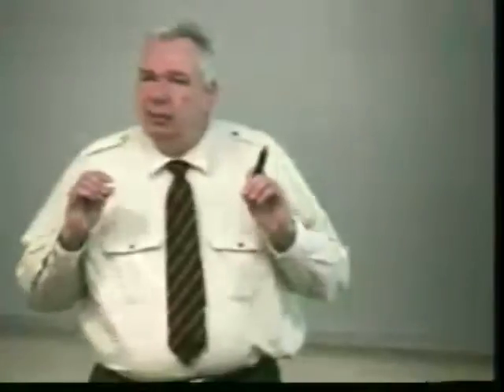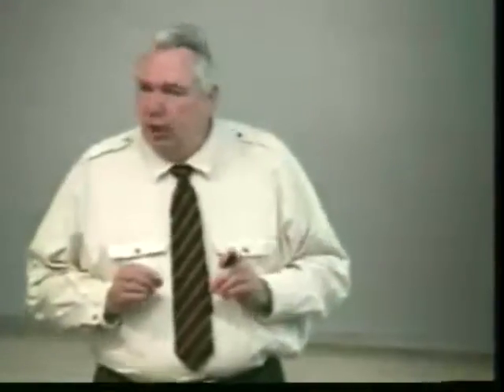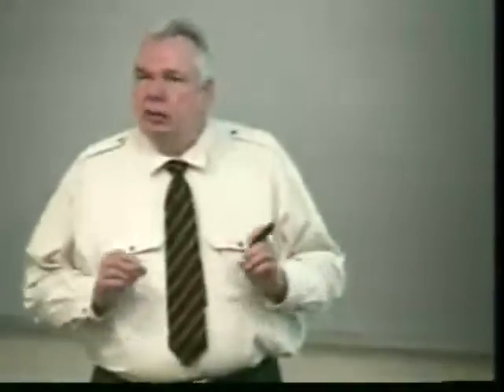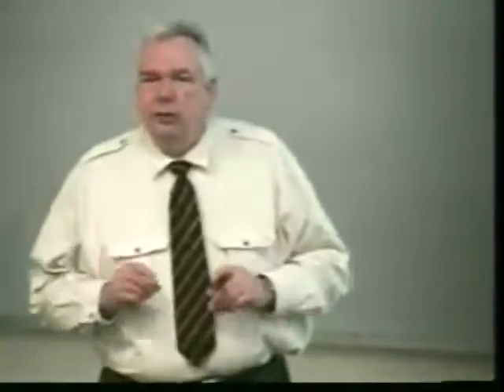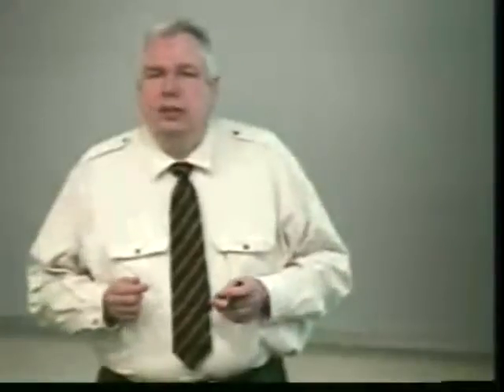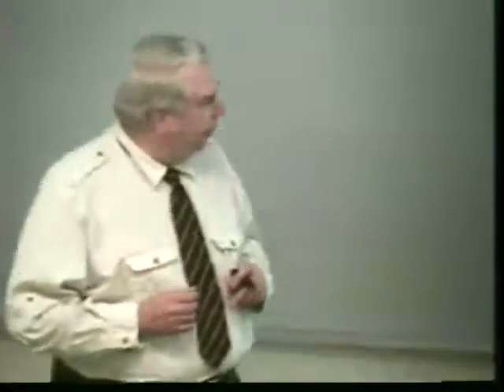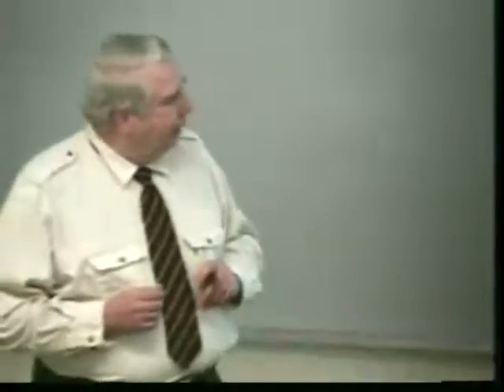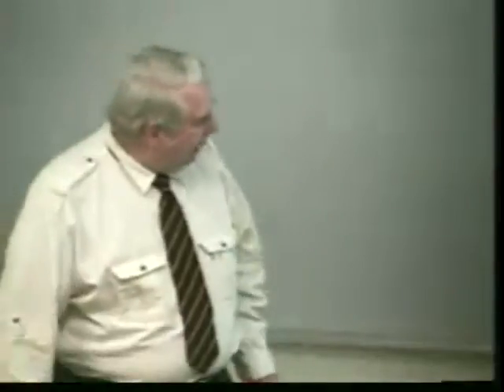The key item is that we reheat multiple times. We provide most of the heat to the power cycle at very close to its peak temperature. And when you provide most of the heat to a power cycle close to its peak temperature, you're much closer to a Carnot cycle. And a Carnot cycle, of course, describes the most efficient cycle for the conversion of heat into electricity. So we're going to be using a Brayton Carnot cycle, a multi-reheat cycle.